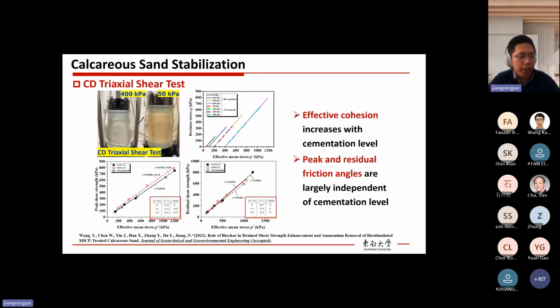In order to better understand the mechanical performance of MICP treated calcareous sand, we performed both CD and CU triaxial shear tests. Firstly, for the CD triaxial shear test, the first graph shows the post-failure state of the sample under low and high confining stress conditions. The second one shows the deviator stress versus effective mean stress relationship. Because it's a CD test, they are simply straight lines. And as we can see for the bio-cemented case, the solid line compared with the dotted line, the solid line goes more to the right. It means that the strength of the soil has been improved.